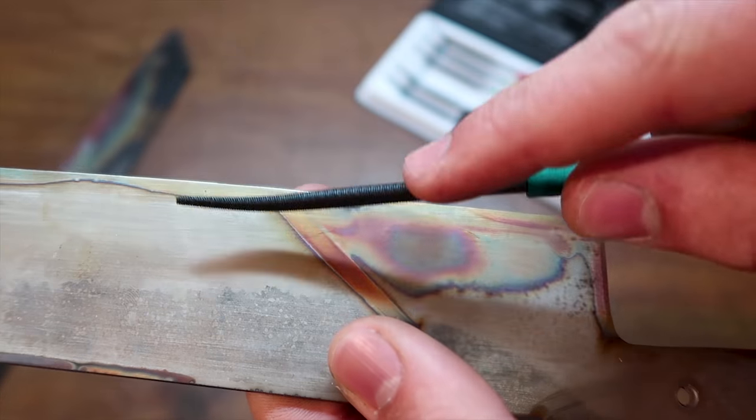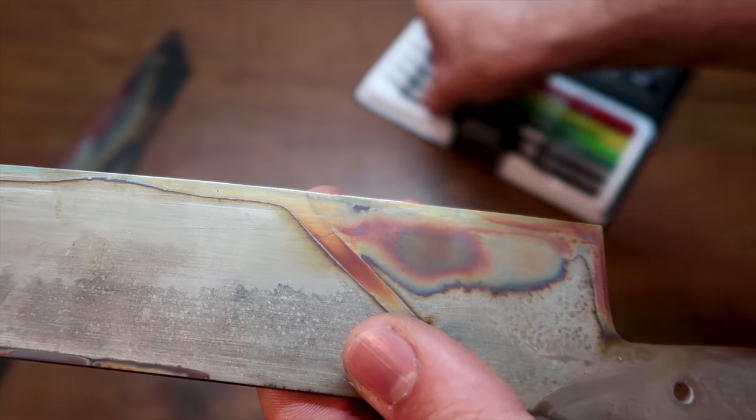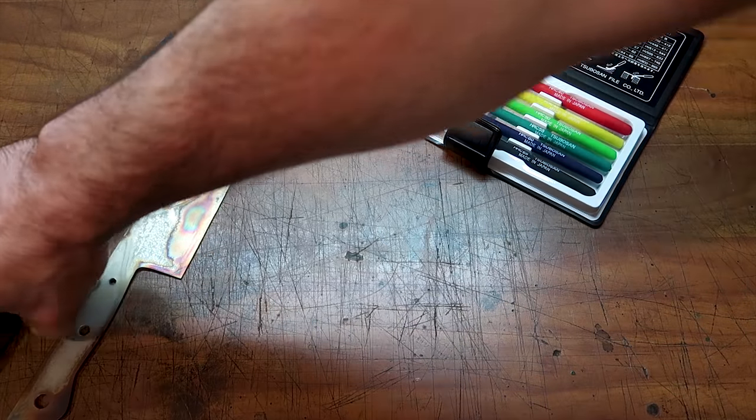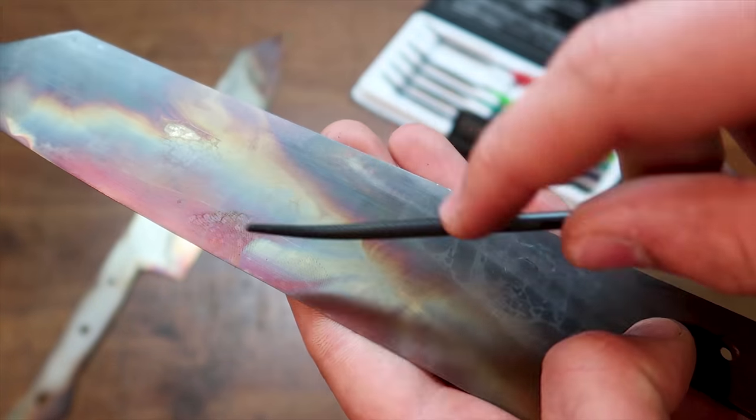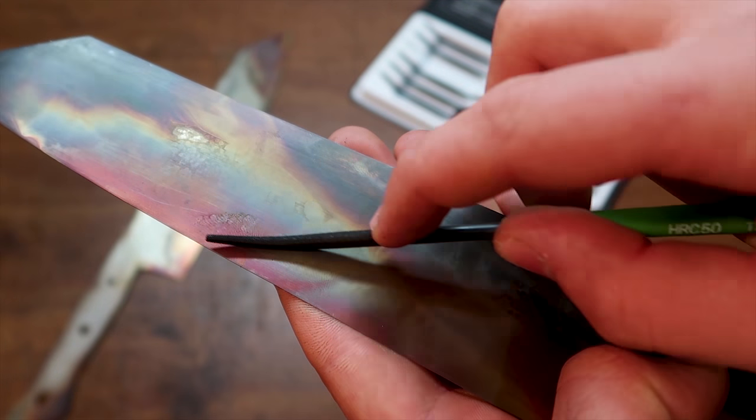For the plate quenched blade, that is the 60 RC. So we know that this blade has a hardness between 55 and 60 Rockwell, and I'm very happy with this number because it is exactly what I was expecting for this steel and the tempering temperature that I applied.